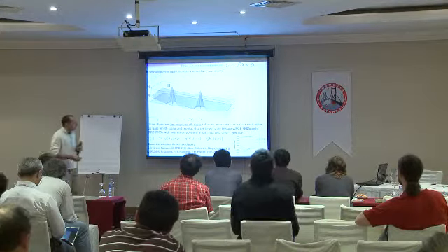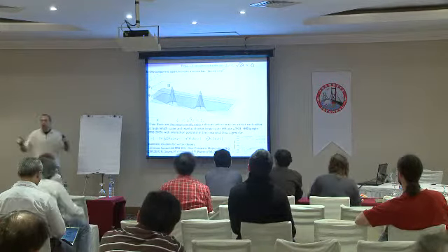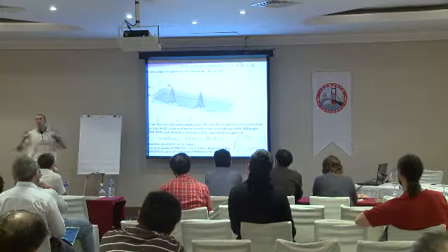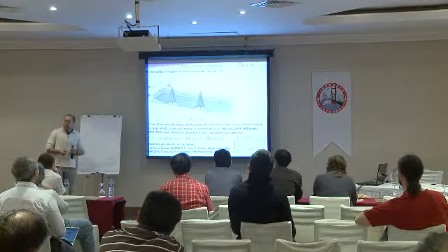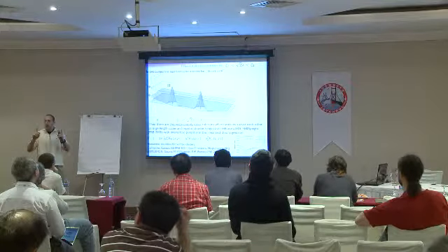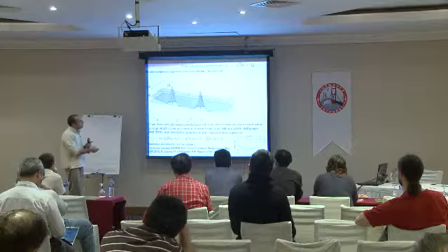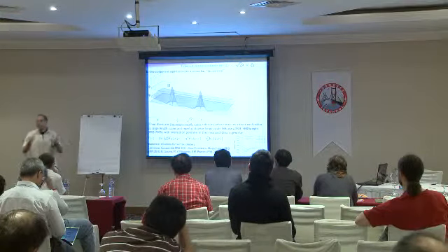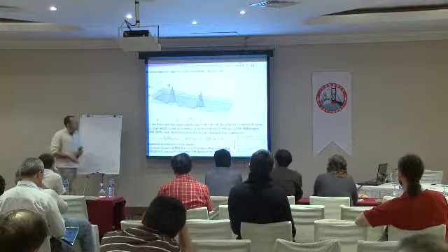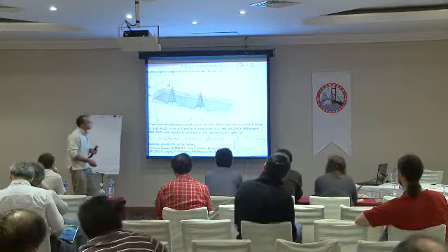And then, if you take two such vortices as shown on this picture, and start bringing them together from a long distance, they will feel each other first by their cores, and core-core interaction is attractive. And when they get closer, they start feeling the magnetic field of each other, and magnetic field interaction is repulsive. Thus, the interaction potential is long-range attractive, short-range repulsive.